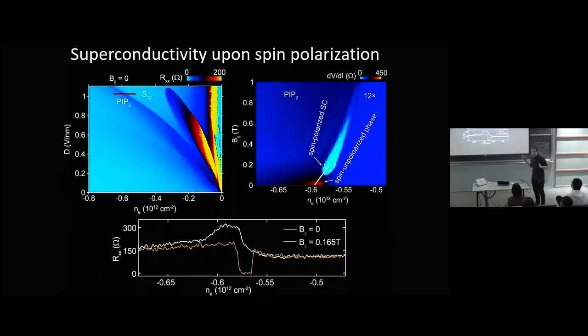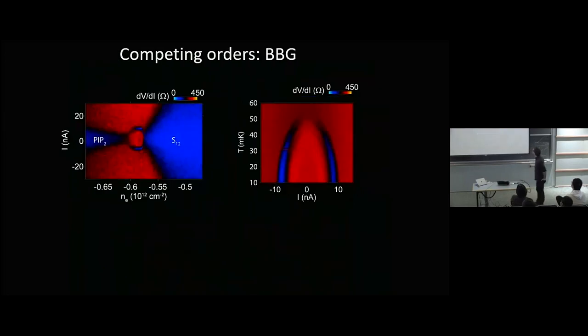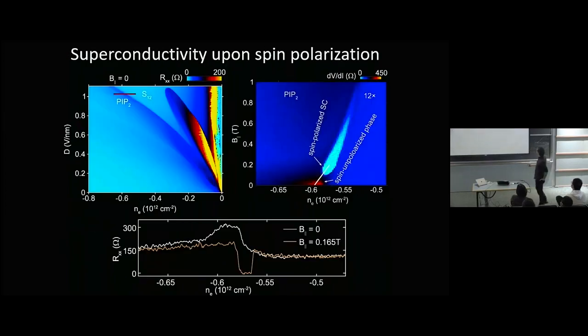Now, what we think is going on here is that there's some competing phase at zero field that doesn't superconduct. Now, what it is, I don't know. But there's some phase at low magnetic field that doesn't superconduct, but then you hit some transition, the system spin polarizes, and thereafter it superconducts, and actually superconducts to far above the Pauli limit. In fact, sorry, I don't have the data here, but the TC of this superconductor is 30 millikelvin, which makes the Pauli limit about 30 or 40 millitesla. It doesn't start superconducting until like twice the Pauli limit, and it continues superconducting to 30 times the Pauli limit.